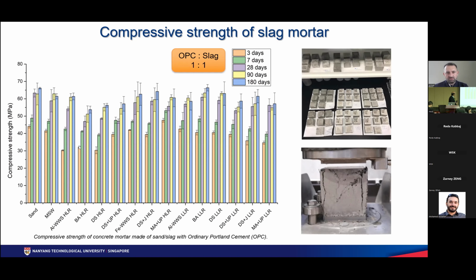So some initial changes could be observed for some of the mixes for the initial strength, but as curing time goes on, they catch up with more or less the sand mortar. And this material perfectly fits for non-structural applications, which requires very low strength. And even looking at this higher strength concrete for structural applications, it actually generates a promise as well. So in Singapore, the use of slag or new sand is already approved for non-structural applications, while for structural application, this is something that we are now currently working on.